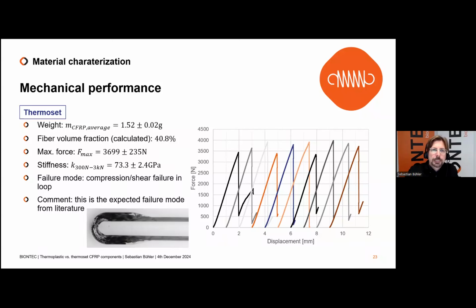If we look a little bit deeper into the mechanical performance for the thermoset, at the end of the day, we have the weight of every part after we have deburred and finished it. We have 1.52 grams per part. And the fiber volume fraction, okay, it's calculated because we have no measurement device available in-house. We have 41%, and we gained a maximum force of 3,700 Newton. The stiffness was around 73.3 gigapascal, and the failure mode was a shear failure or compression shear failure in the loop, as you can see in the picture below.